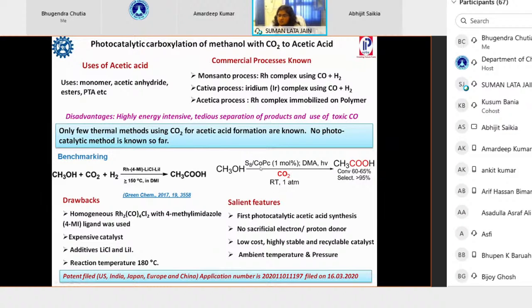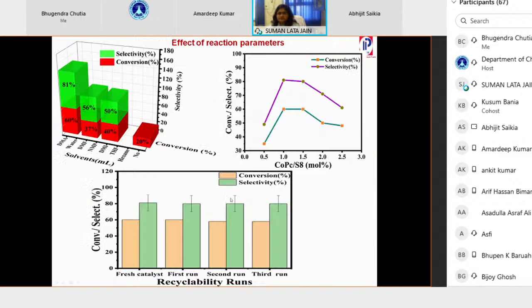advantages. We used a cobalt-based complex, which compared to rhodium is very inexpensive. This octasulfur we used as a support for immobilization, to make this heterogeneous. The reactions we carried out under atmospheric pressure and room temperature in the presence of light. We got selectivity of acetic acid of more than 95% with conversion in the range of 60 to 65%. The main attractive thing is that we did not use any sacrificial electron or proton donor. It is very recoverable; we could easily recover and recycle it.